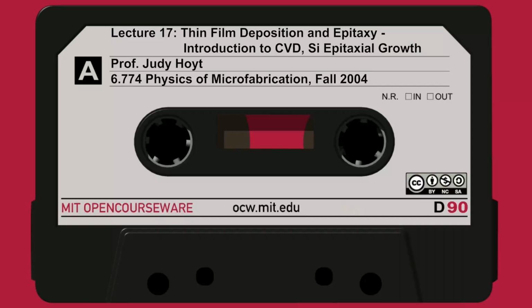These could be used for dopants, for boron and phosphorus doping. You had carrier gases like argon and hydrogen. Hydrogen chloride could be used to etch deposits off the quartz. And here's a liquid source for silicon tetrachloride, SiCl4. Maybe hydrogen was bubbled through that and transported that vapor into the chamber.